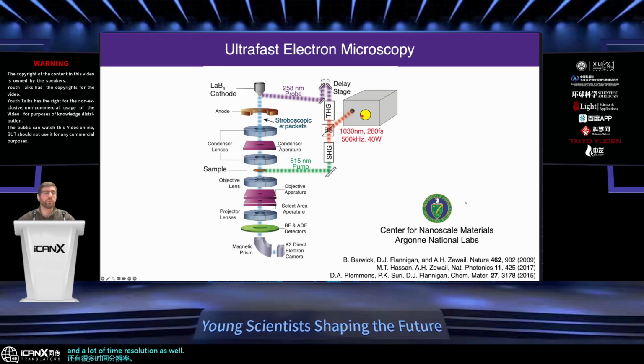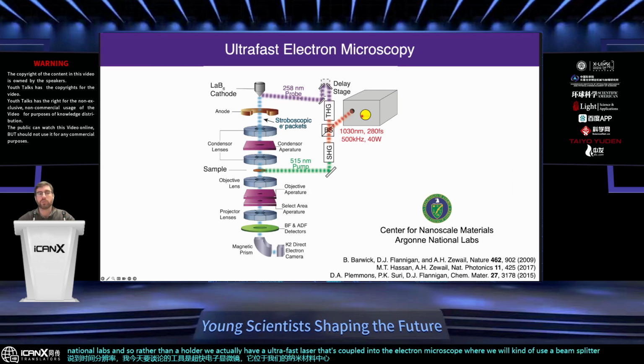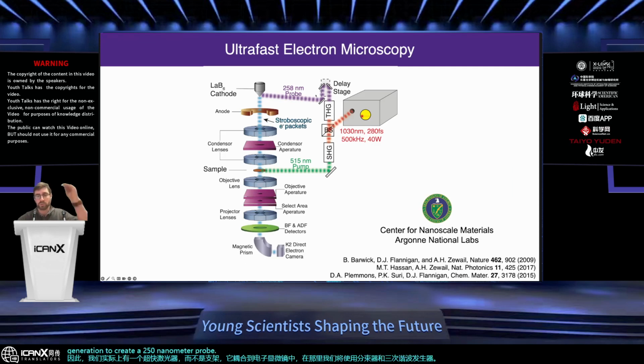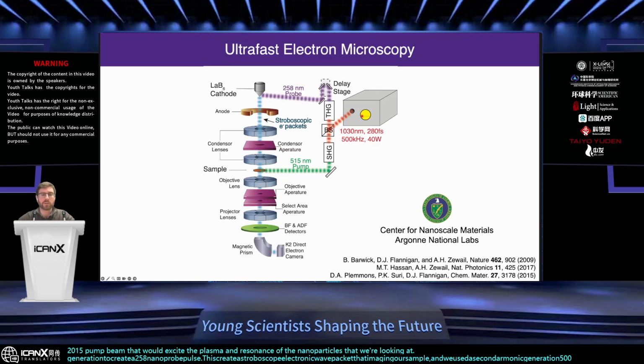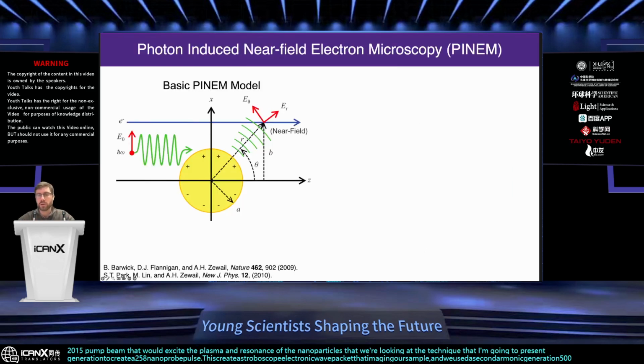And so speaking of time resolution, the tool that I'm going to be talking about today is the ultrafast electron microscope that's housed in the Center for Nanoscale Materials at Argonne National Lab. Rather than a holder, we actually have an ultrafast laser that's coupled into the electron microscope, where we use a beam splitter and fourth harmonic generation to create a 258 nanometer probe pulse. This creates a stroboscopic electron wave packet that images our sample. And we use a second harmonic generation 515 nanometer pump beam that excites the plasmon resonance of the nanoparticles that we're looking at. The technique that I'm going to present on today is called photon-induced near-field electron microscopy.